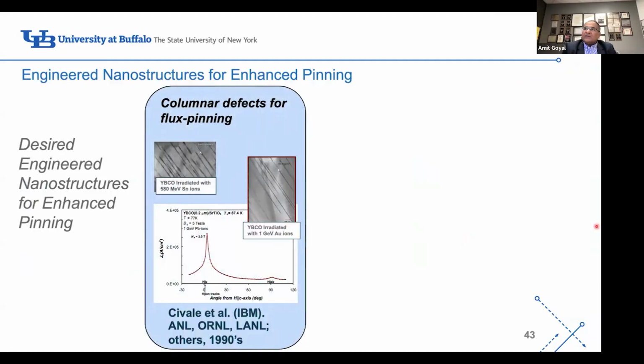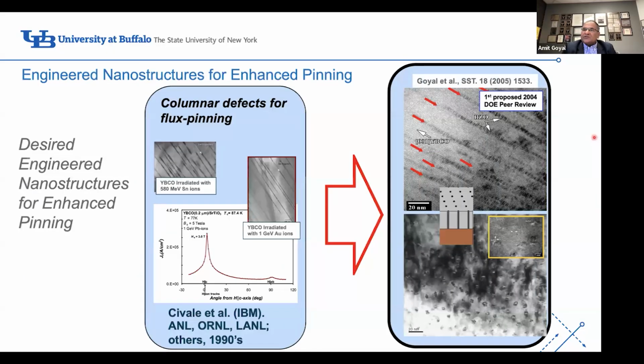So, in order to address the need, we came up with this innovation. When we deposit the superconductor, we automatically create, using a process called simultaneous phase separation and strain-driven self-assembly, essentially the same microstructure, where when you look at the cross-section of the superconductor film, you have nanocolumns. You're looking at Moiré fringes here, nanocolumns of, in this case, barium zirconate.